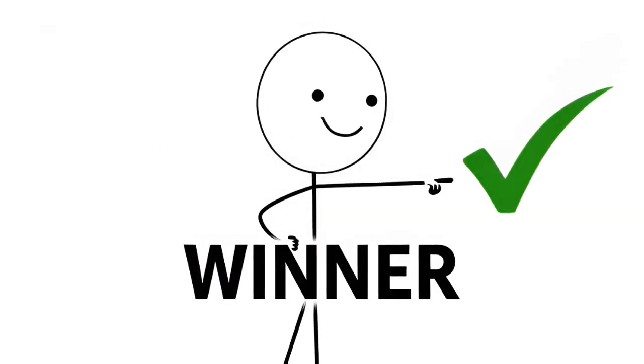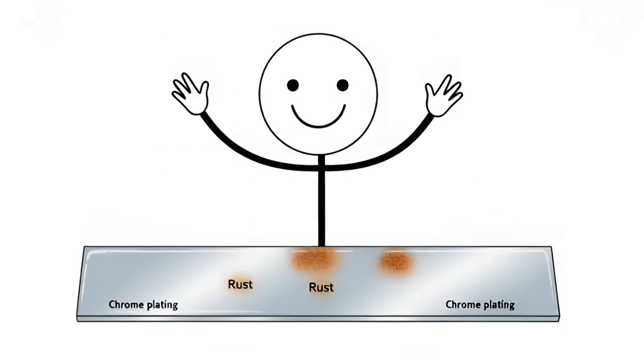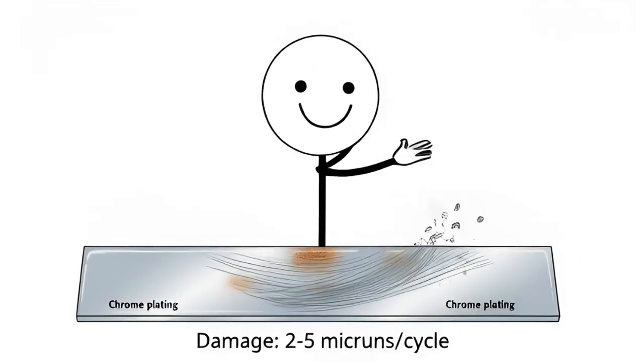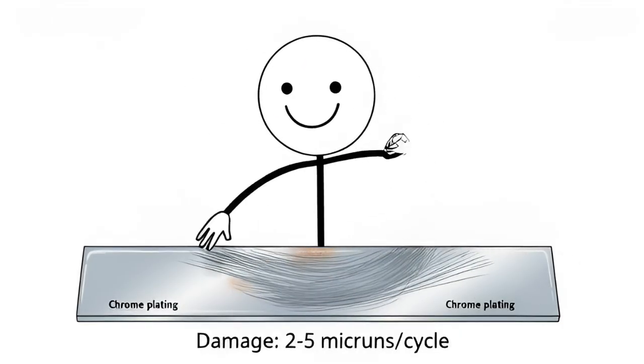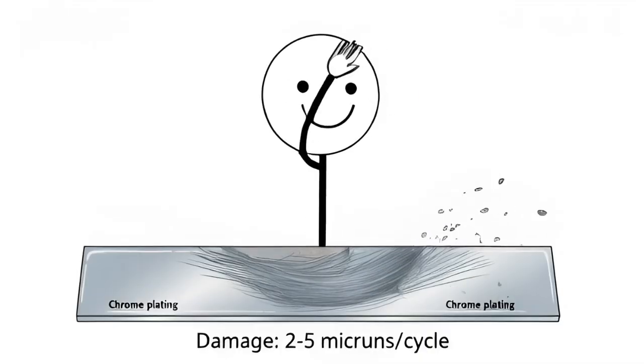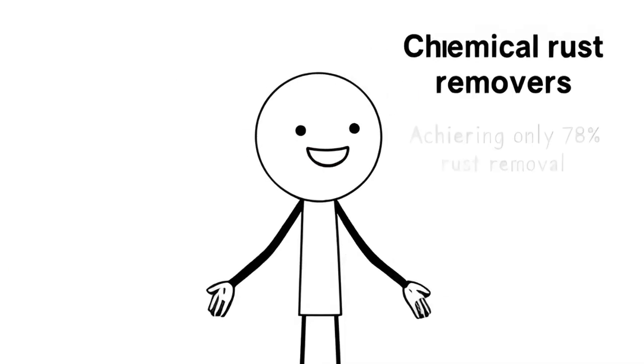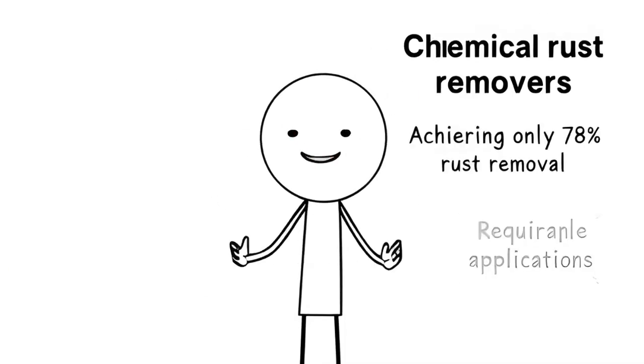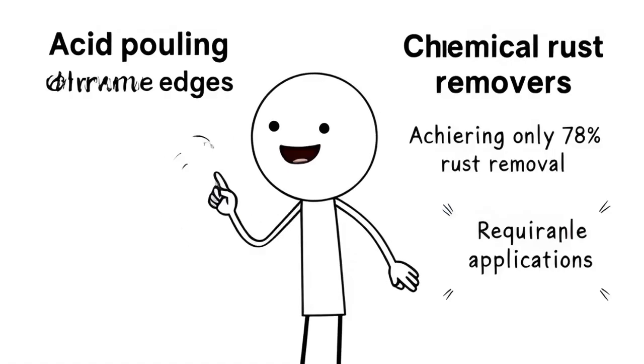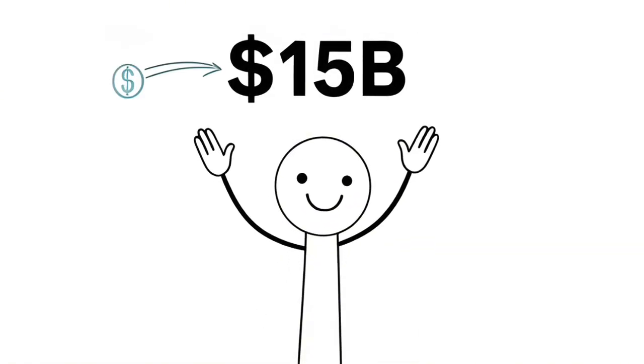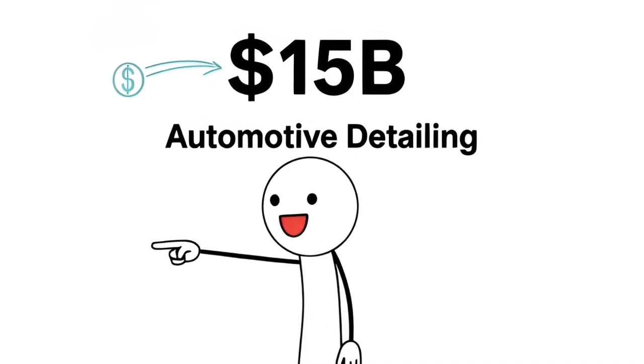The aluminum and vinegar method achieved complete rust removal in 94% of test samples without measurable chrome layer thickness reduction. Mechanical abrasion removed rust but also removed portions of the chrome plating, measured at 2 to 5 microns of thickness loss per treatment cycle. Chemical rust removers achieved 78% rust removal, but required multiple applications and abraded chrome edges where acid pooled during treatment.